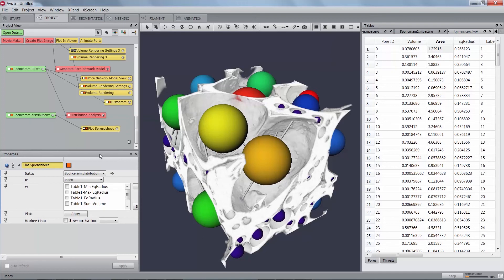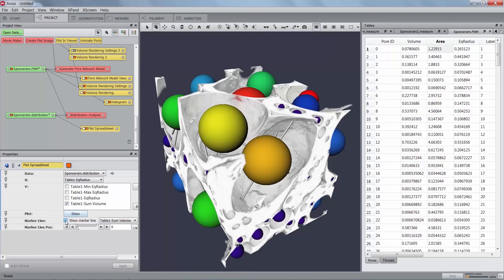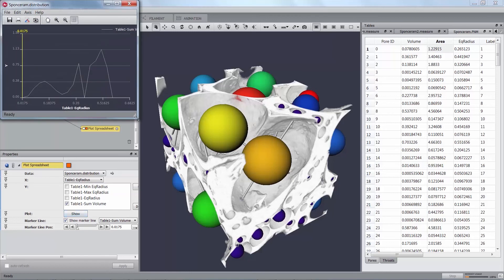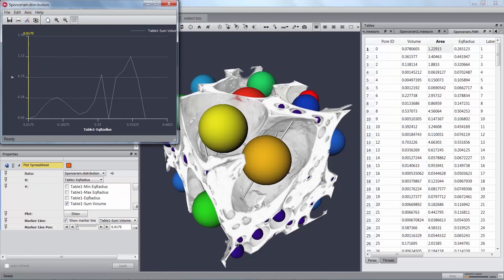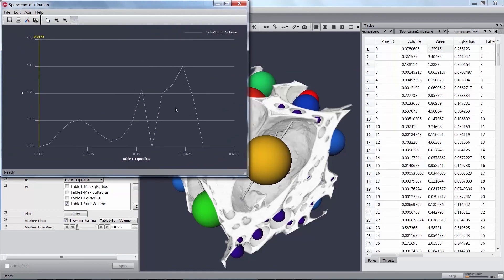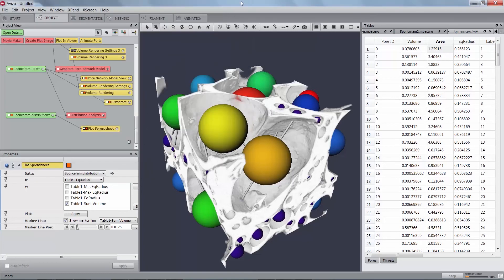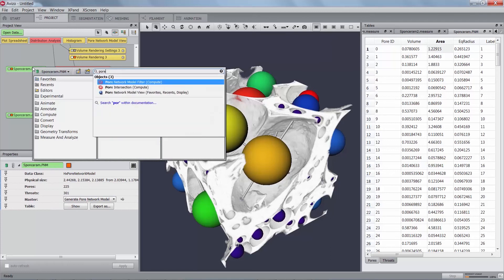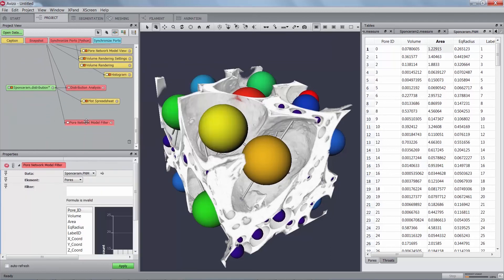Attach a plot spreadsheet module to the result and set the X port to table 1 equivalent radius, y to table 1 sum volume, and check the show marker line checkbox. Clicking show in the plot port will generate the plot, which shows that the majority of the pore space is filled by big pores but the predominant small pores have a radius around 0.15. It is also possible to filter the data to keep only pores with volumes greater than 0.02 for example. Create a pore network model filter module on the generated pore network model and then add volume greater than 0.02 in the filter port by double clicking on volume and typing in the rest.